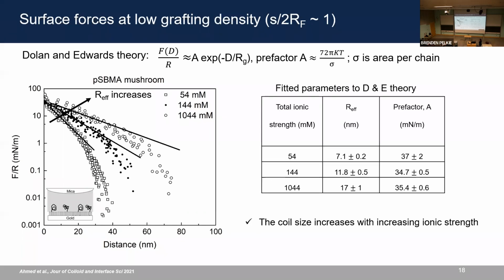And this increases with the salt concentration. However, the prefactor remains the same, because it's a function of the grafting density, and we have not changed the grafting density in these measurements.